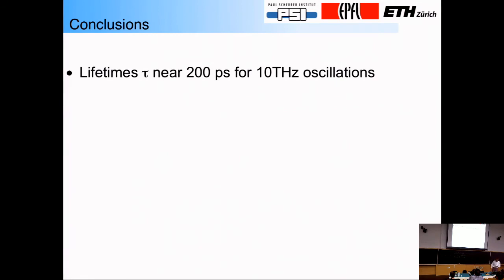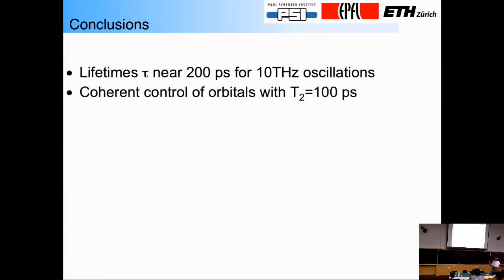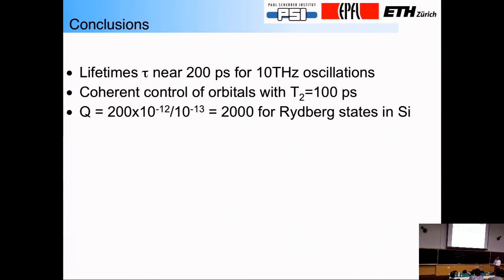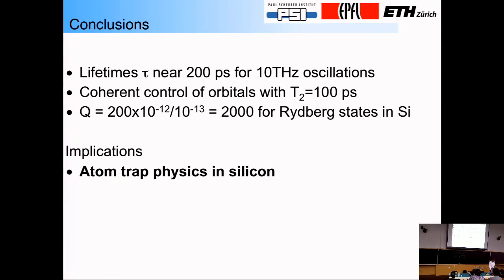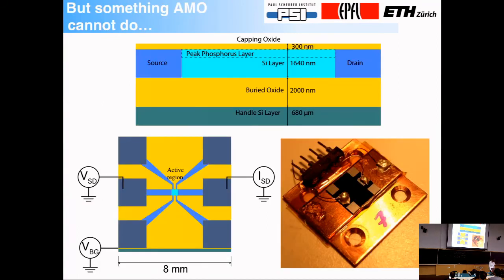So the conclusion of this is that I have lifetimes, in fact, near 200 picoseconds for these 10 terahertz oscillations. So we're able to coherently control these orbitals. And so the Q, if you like to speak of that language, is something like 2000. And this has really interesting implications. This now means that we can do atom trap physics in silicon. We can control the atoms. We can control their wave functions with light. And we've heard a lot about spintronics, but actually we can also do orbitronics now.